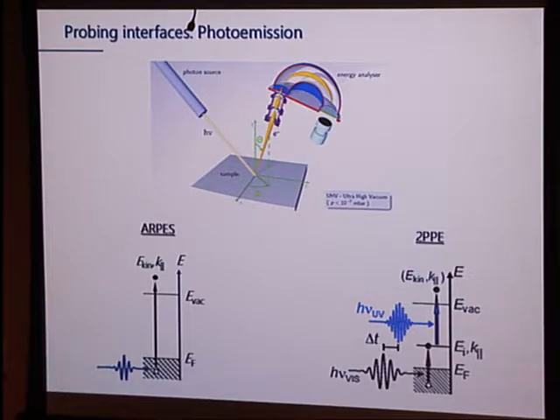This is good. We're going to use some of that. But you can do this in a slightly more sophisticated fashion. Instead of using one big photon, use two small photons. Make them short laser pulses, and that allows you to do pump-probe spectroscopy for one, which gives you, if the laser pulses are femtoseconds, femtosecond time resolution. And for another, it gives you conduction band information, which you will never be able to get from this, because you can only eject an electron from the valence band or lower, because you need an electron to be in there in the first place.